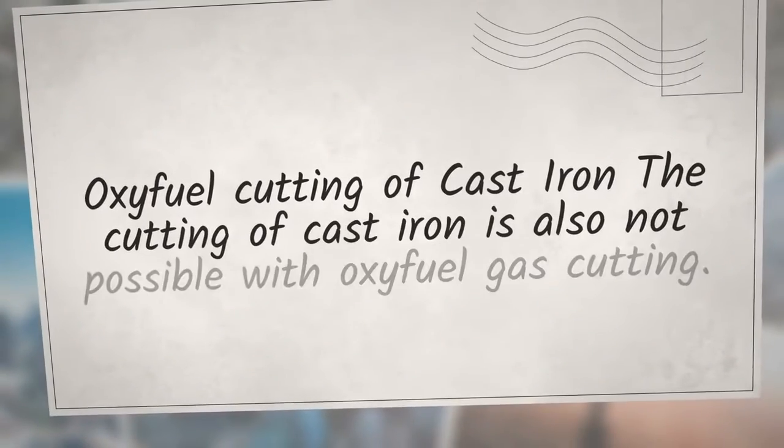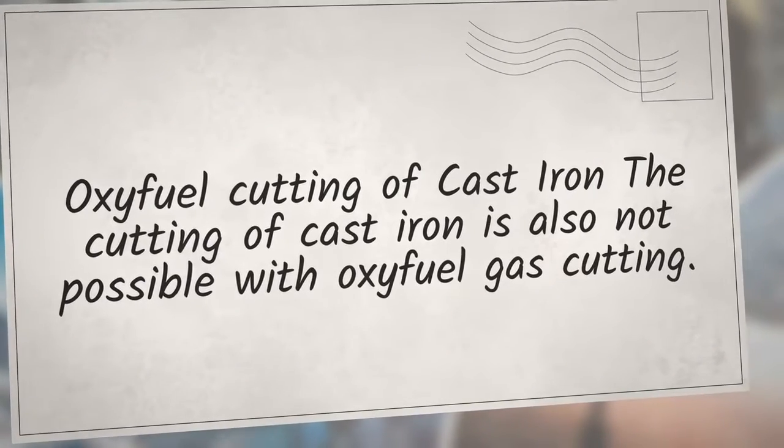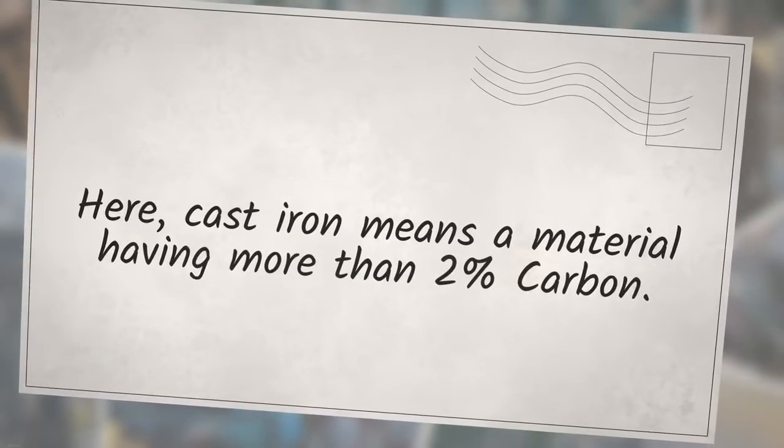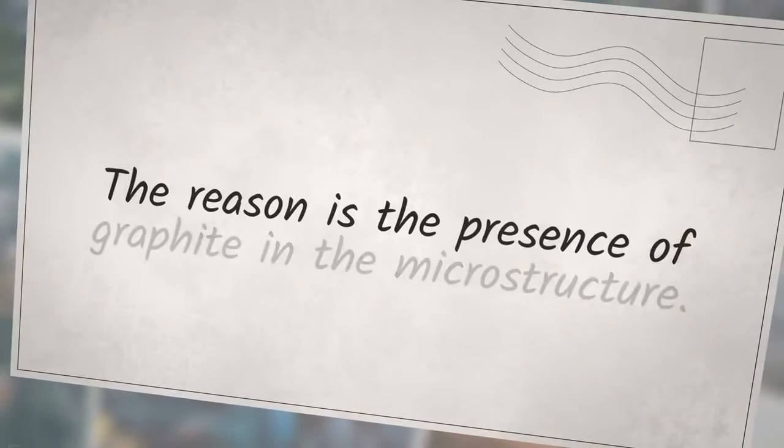Oxyfuel cutting of cast iron: The cutting of cast iron is also not possible with oxyfuel gas cutting. Here, cast iron means a material having more than 2% carbon. The reason is the presence of graphite in the microstructure.